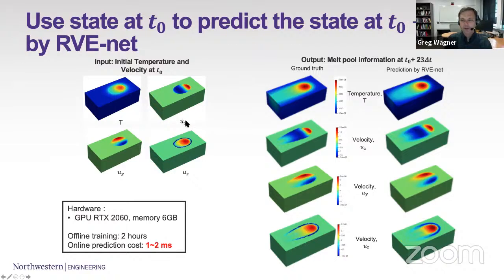So for a given melt pool, we can predict, with the ground truth on the left being the simulation data and the neural network prediction on the right, for a time 20 or so time steps later. Not perfect, but it matches the temperature and velocity very well for a particular melt pool size. And again, we're working on testing this out for different cases, improving the amount of data, and eventually coupling this to the full part scale simulations. Each individual melt pool prediction, and this is the key, can be done in a handful of milliseconds. So this is extremely fast.